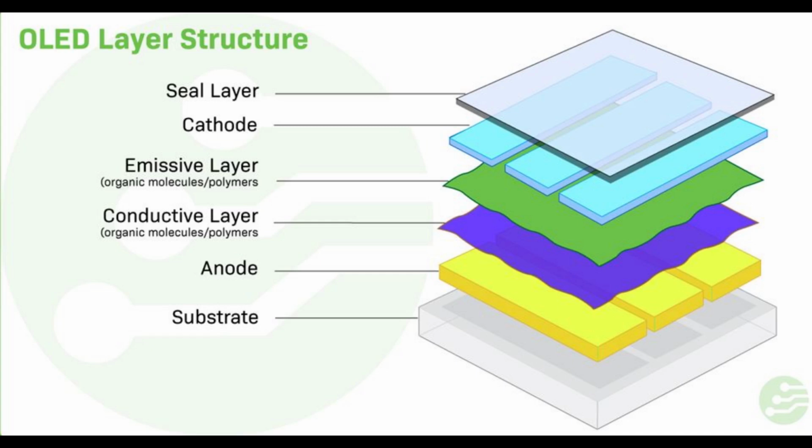Polymer light-emitting diodes, PLED, POLED, also light-emitting polymers, LEP, involve an electroluminescent conductive polymer that emits light when connected to an external voltage. They are used as a thin film for full-spectrum color displays. Polymer OLEDs are quite efficient and require a relatively small amount of power for the amount of light produced. Vacuum deposition is not a suitable method for forming thin films of polymers. If the polymeric OLED films are made by vacuum vapor deposition, the chain elements will be cut off and the original photophysical properties will be compromised.